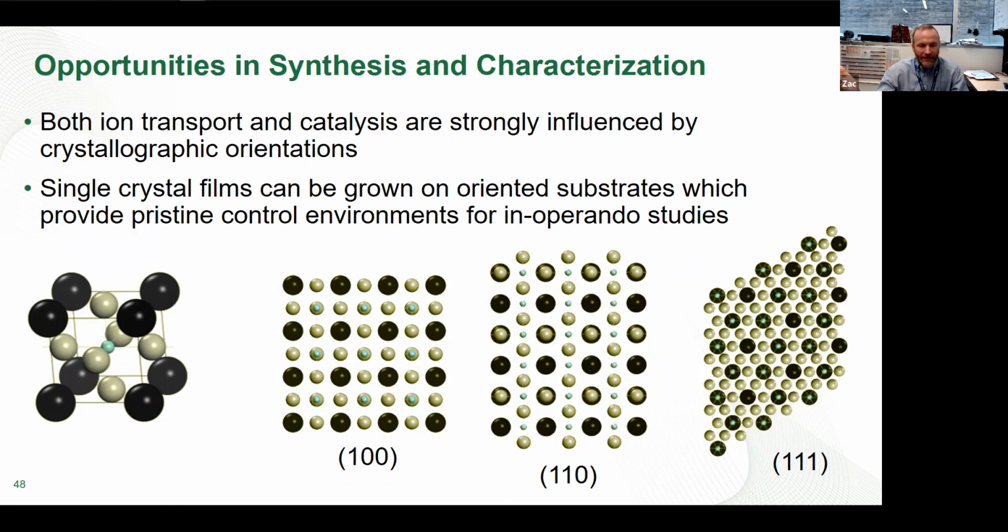What happens when we figure out how to control those individual parameters, exactly what our crystal structure needs to be, which facet? This is one thing I'm showing on the screen now. With the thin films, we can actually grow on different substrate terminations. So if theory was able to predict what the energy states at our surface were, we can go back in and grow a crystal on these facets, so we can individually isolate what the facet is, and get this really nice feedback between theory and experiment.